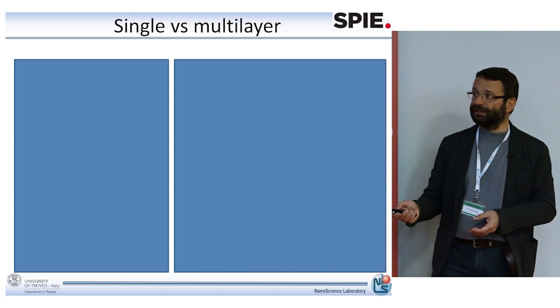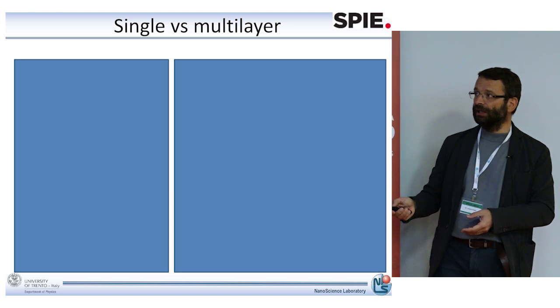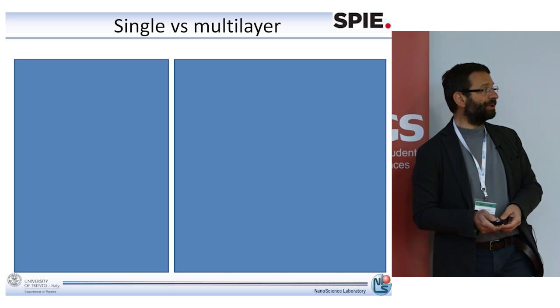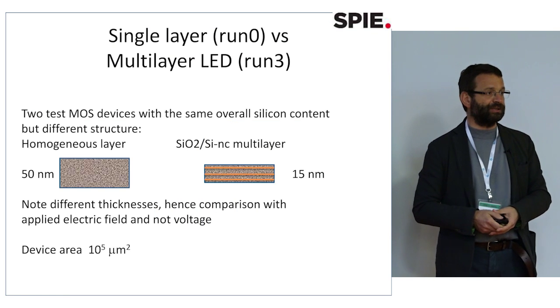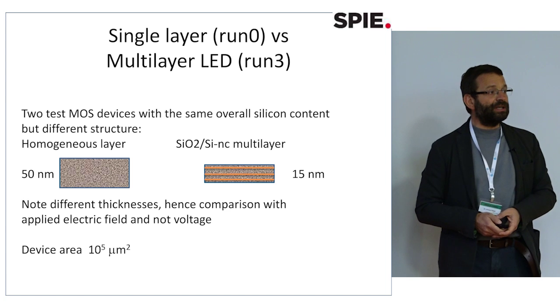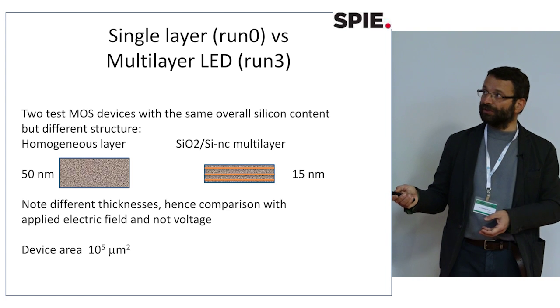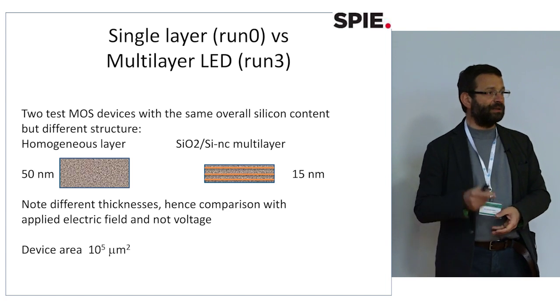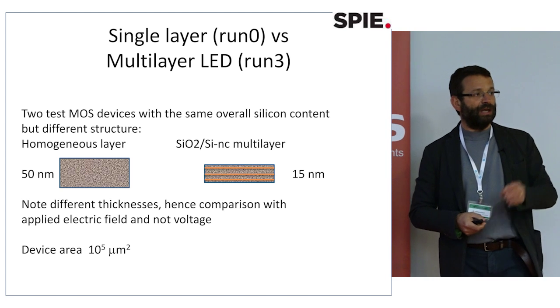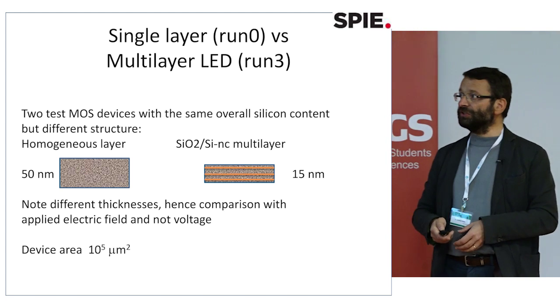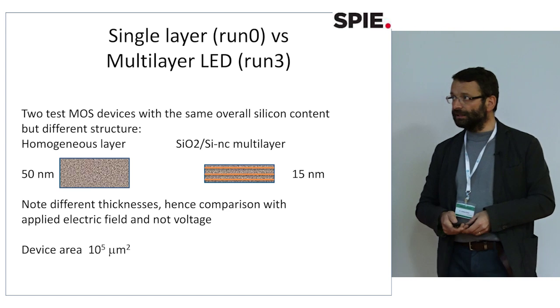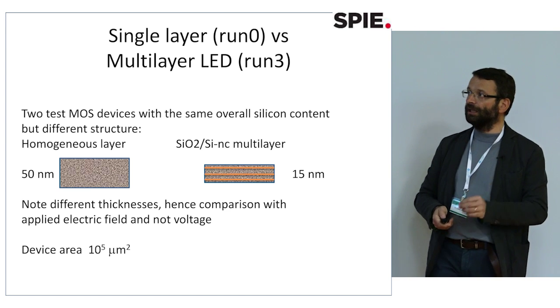The idea we had was to move from a single layer of randomly dispersed nanocrystals to a multilayer of silicon nanocrystals. The reason why we want to have the multilayer is that now the electron current is forced to go through the layer of the nanocrystals. But here the issue is that we need to control the thickness of the silicon oxide between the different silicon nanocrystals at the nanometer scale. So from the point of view of fabrication, this is a very critical approach.